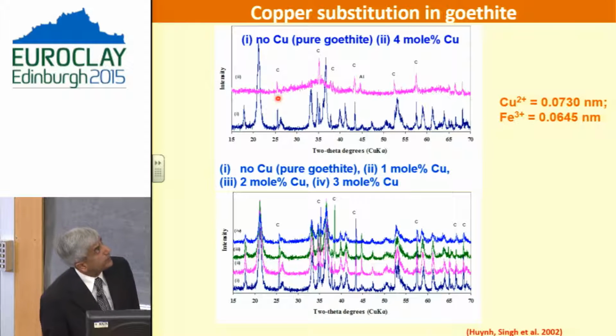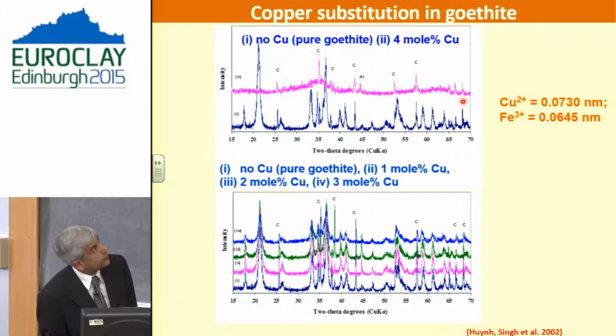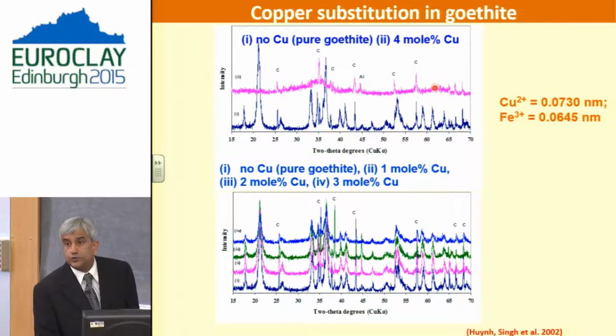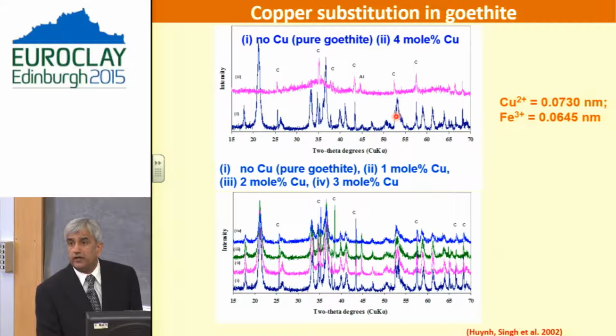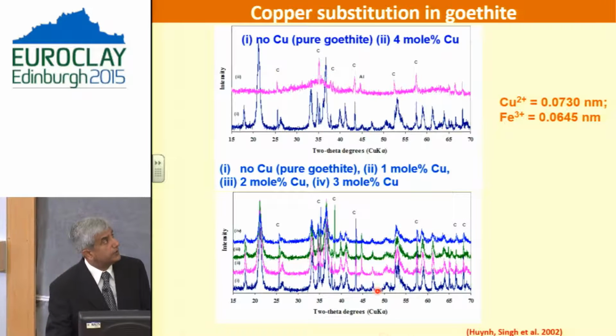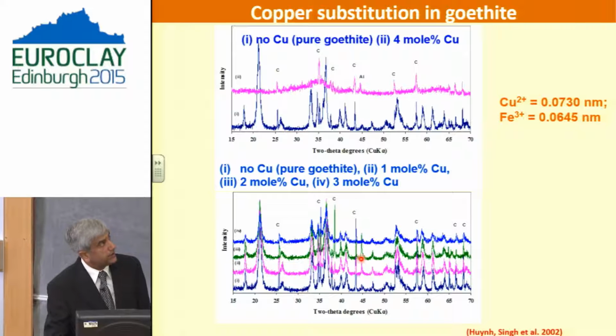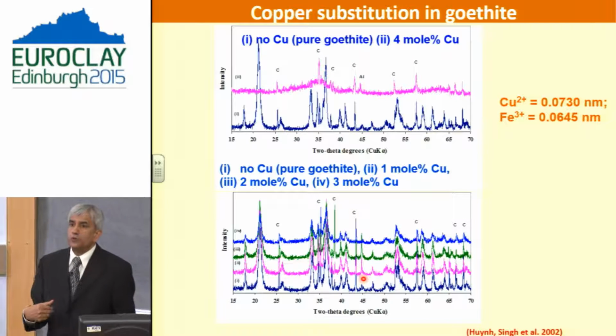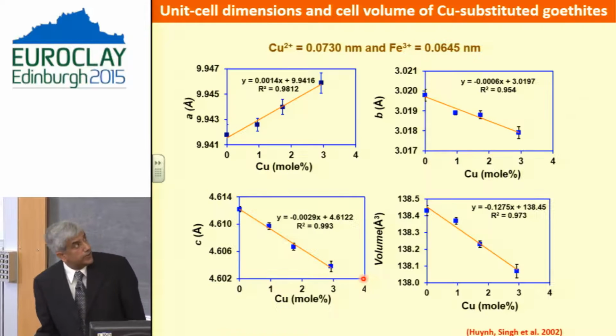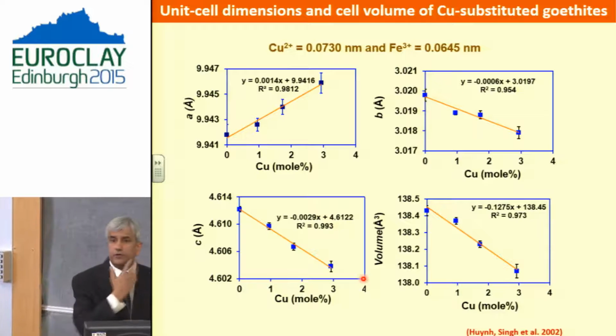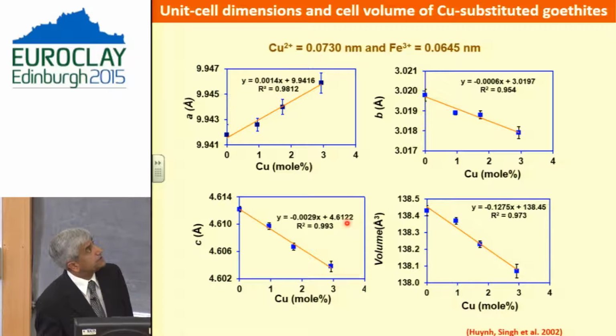In case of copper, this is the sample with the 4 mole % copper substitution. So you can see that there is hardly any goethite when you have 4 mole % copper. Up to 3 mole %, there is some incorporation of copper. When you look at the unit cell parameters, we did the synchrotron X-ray diffraction of these samples.